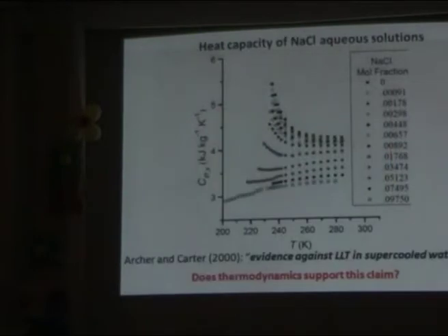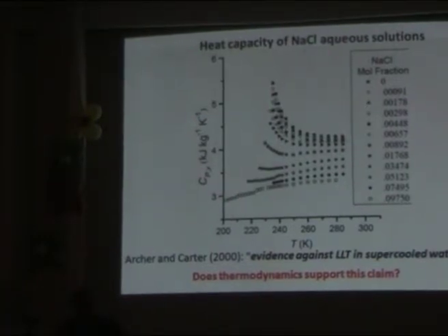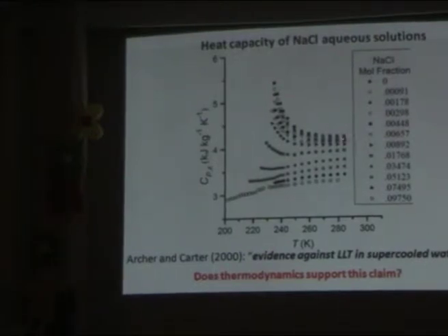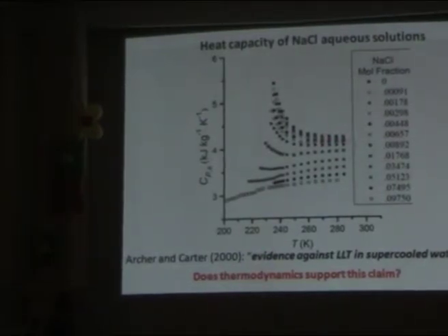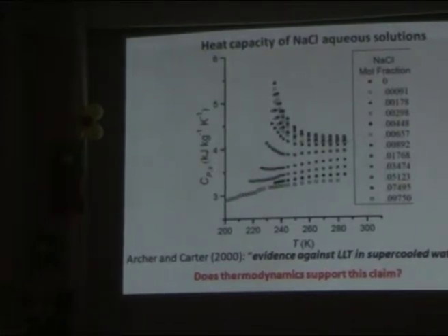Next slide. The only experiments for salt water in the supercooled region are actually beautiful experiments by Archer and Carter from the United States National Institute of Standards and Technology, just 30 minutes driving from my university to their place. They studied heat capacity and concentration in pure water, which is described very well by two-state thermodynamics, and they found the heat capacity dramatically suppressed in solutions. Disappeared completely after a few percent of salt, no anomaly. They concluded there is evidence against liquid-liquid transition in supercooled water.